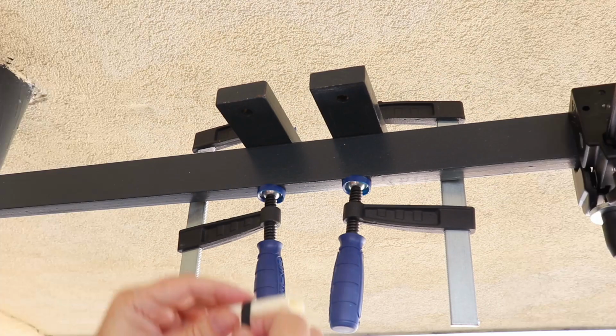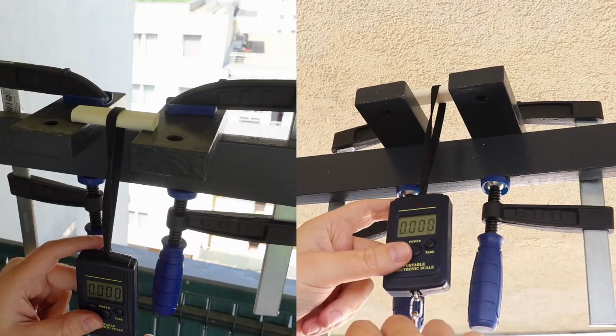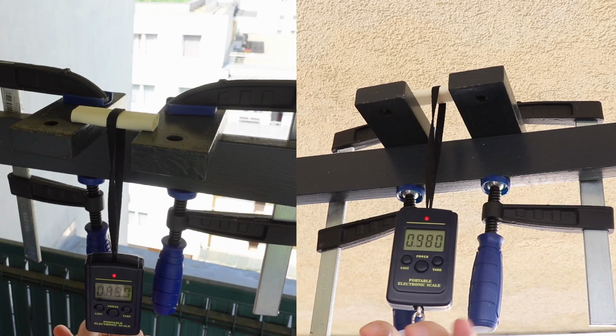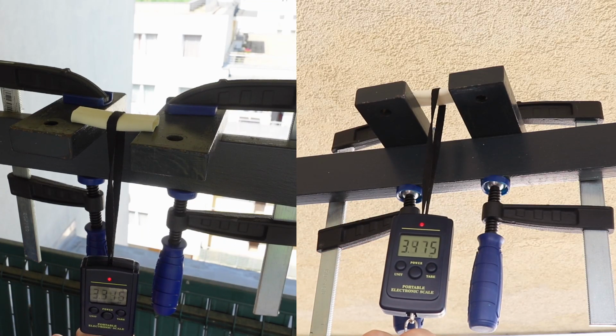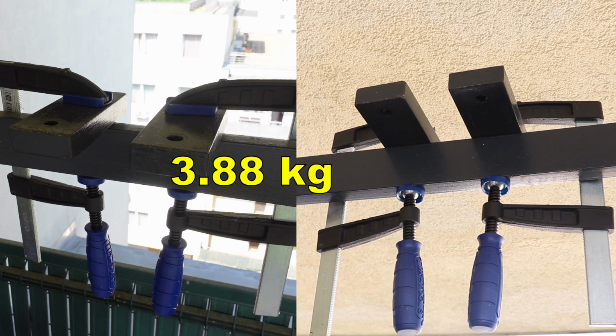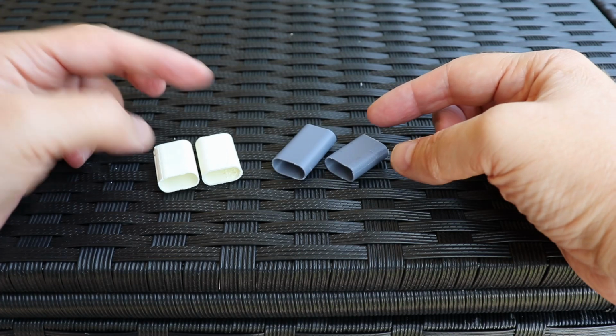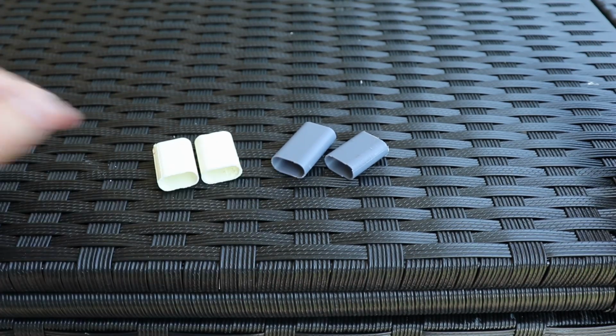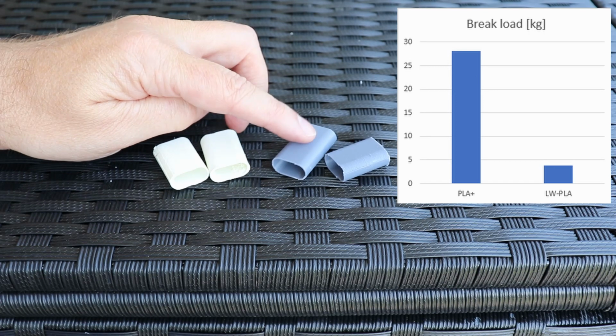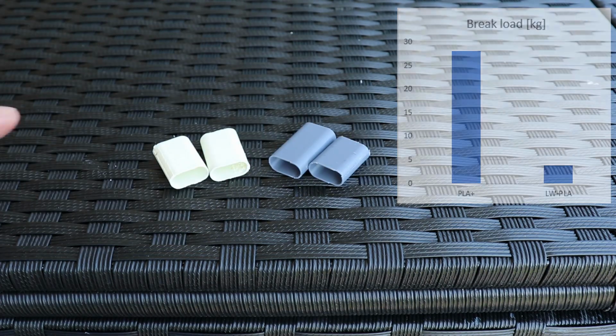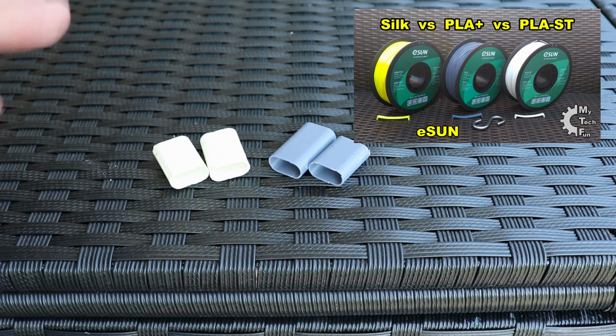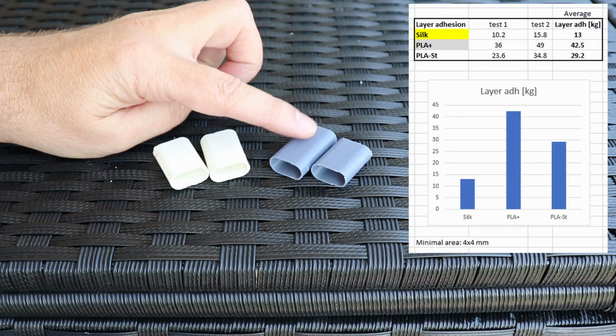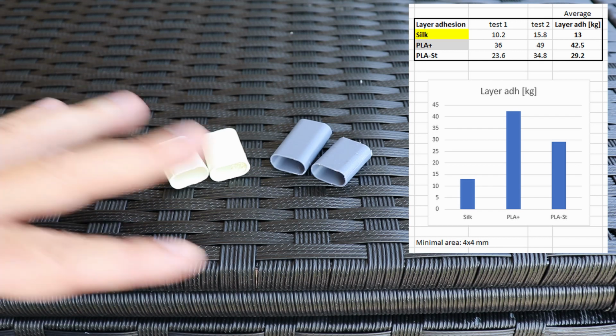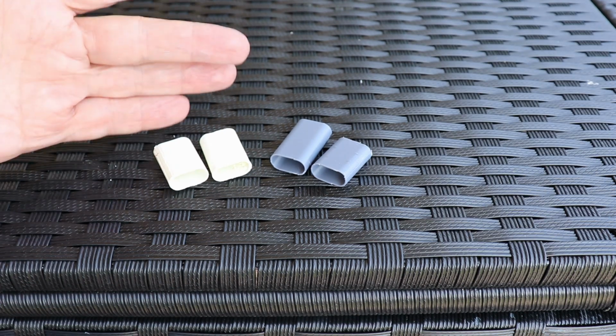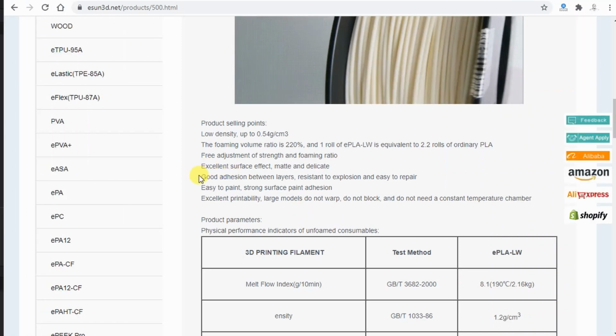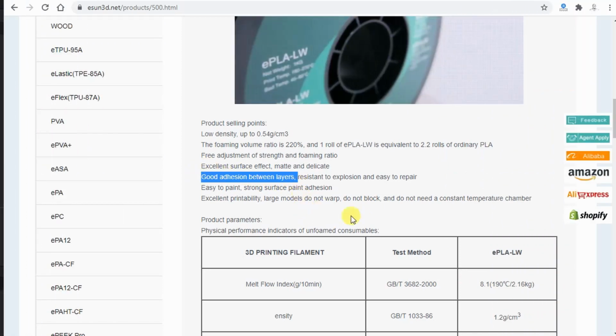That was strong. And now lightweight PLA. And this is how they broke. They actually bend a little bit until they separate on one of the layers. Well, definitely PLA Plus is much stronger, and if you check my PLA test, definitely for all types of PLA, this PLA Plus has the strongest layer adhesion, so it's not comparable, but just for the reference I compared with these two. On the product website they mentioned that this material has good layer adhesion.